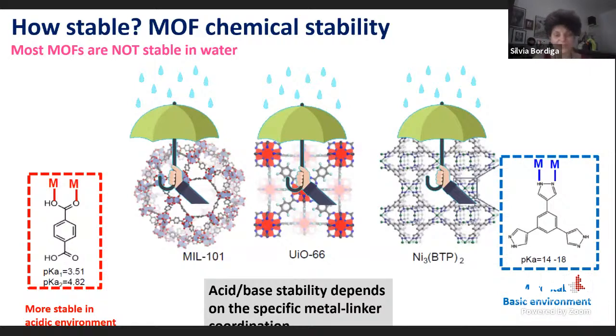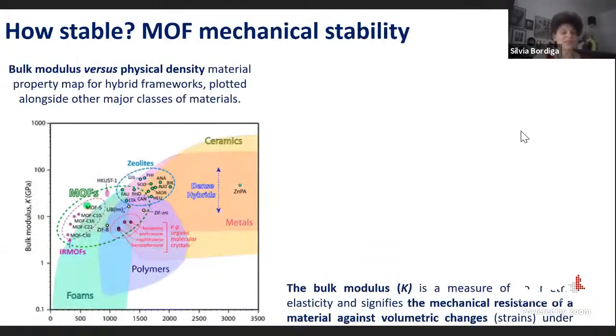In particular, if we think about the stability with respect to chemicals, the MOFs constituted with building blocks with the carboxylate moiety are more stable in acidic environments, while the MOFs with linkers containing nitrogen are more stable in basic environments. And so we need to pay attention when we decide how to use the material.